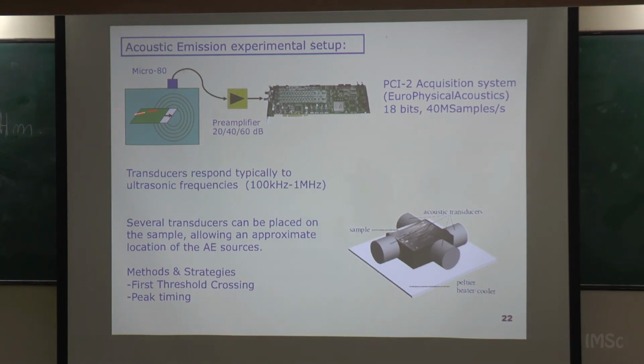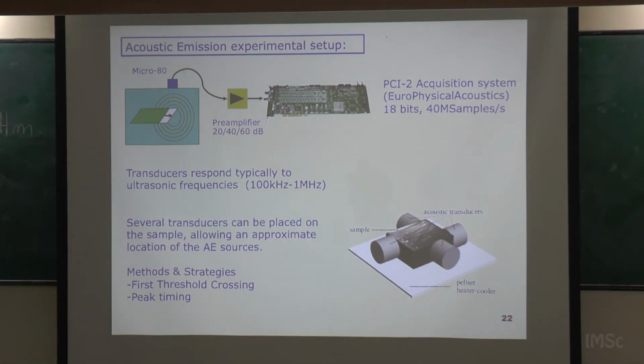So we put the sensors, we have the acoustic emission like this, we amplify, etc. We can also do what is called the location. If you can put many sensors on your sample and take into account the time of arrival to every sensor, you can locate where the phenomenon, the source of the acoustic emission, is placed. So in some measurements, we can use this location mechanism.